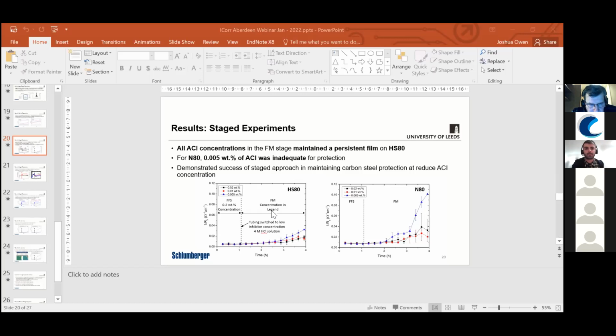First, what we need for analysis is a method which minimizes impact on the system. When we use polymerizable inhibitors, what happens when we start anodic polarization, even 5 millivolts in the anodic direction, is that you'll start very strong corrosion. Inhibitors start to desorb because you lose metal. It means you lose bonding between the polymer film and metal. So that's why we try to minimize the impact of our measurements. We use LPR very periodically, maybe only every 20 minutes. But even this might affect the adhesion of the inhibitor film to the surface.